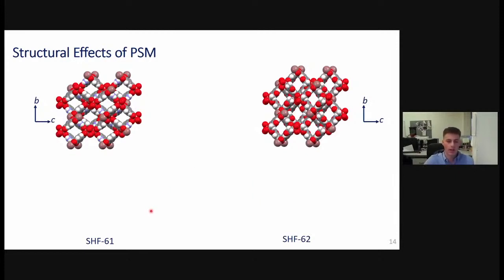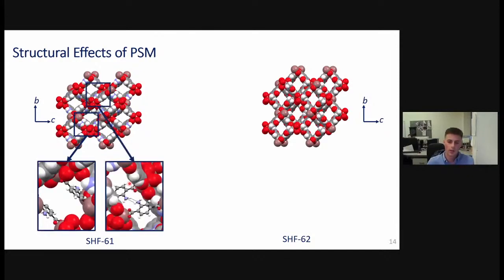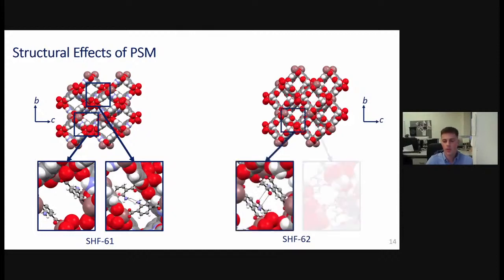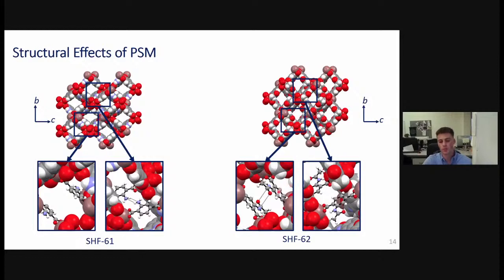So if we look at the two frameworks side by side, again, looking down the A-axis, down that channel length, on the left we have SHF-61, and on the right we have SHF-62, our modified framework. So initially they look quite similar. We've maintained our overall interpenetrated diamondoid topology, but there are some subtle differences. So we have two different sites in the framework where adjacent linkers on the two different networks either point away from each other, in which case they're unable to form an interaction, or in the second case, they point towards each other. So for SHF-61, they form this hydrogen bonding motif between the two amine groups. If we look at the same two positions on the modified framework, what we see is those positions have swapped. We now see those amine interactions replaced by carbonyl to carbonyl interactions of the modified amide groups.